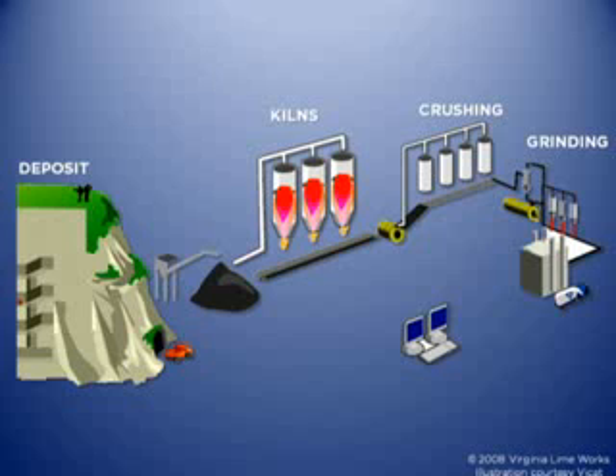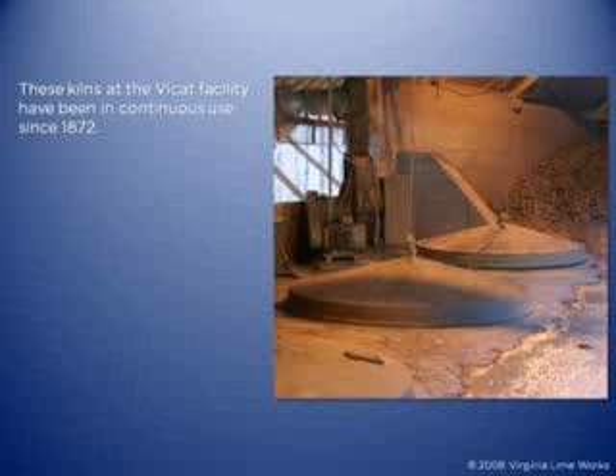And traditional. You often hear the comment that you can't use a historic mortar because they're not strong enough. Well, we can make historic mortars that range from 100 psi to 5,000 psi without any Portland cement whatsoever. So to say that historic mortars are too soft, I just don't take that argument. The kilns at Vicat have actually been in continuous use since the 1870s, 1872. I took that picture. It was actually a pretty big thrill to be standing on top of these century-old cement